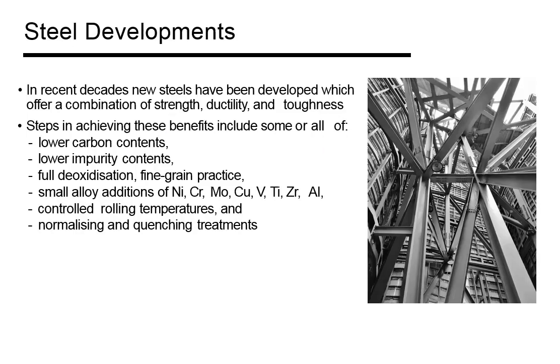Steel developments. In recent decades, new steels have been developed which offer a combination of strength, ductility, and toughness. Steps in achieving these benefits include some or all of lower carbon contents, lower impurity contents, full deoxidization and fine grain practice, small alloying additions of nickel, chrome, moly, copper, vanadium, titanium, zirconium, and aluminum, controlled rolling temperatures, and normalizing and quenching treatments. And once again, this is just a one slide look at steels over the last 50 years, but these are some of the things they're doing to make cleaner, better steels that are better than something that was made in the 20s or 30s.